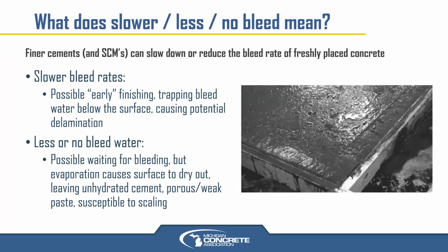But again, the finer cements and other supplementary cementitious materials, SCMs, affect bleed rate, or slow it down, reduce it altogether, hold the water in place. And so why is that an issue? If we have slower bleed rates, if it's just slowing it down, and we're saying it does, what could happen is you could, on an interior slab particularly, get on it to start putting that final finish on it, nice smooth, power troweled finish. You might get on it too early if the bleed is still going to come.